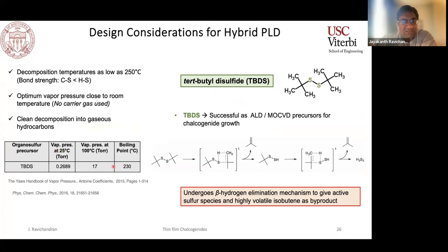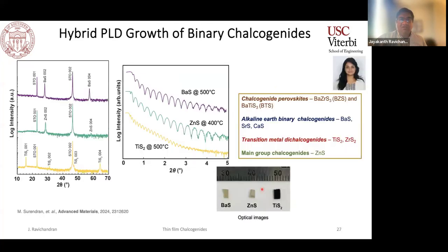And we went through this whole list of precursors, and we identified tert-butyl disulfide as a good choice because you do get fairly appreciable vapor pressure at modest temperatures like 100 degrees Celsius. And presumably, if you have a single sulfur connecting alkyl chains, the cleanliness with which they cleave and interact with your material seems to be significantly better with tert-butyl disulfide. And that's why it's also widely used as an ALD or MOCVD precursor for chalcogenides. So we learned about this beta hydrogen elimination mechanism, which makes this much more conducive to getting cleaner, nicer growth of these materials. So we chose this as our precursor material and we started trying to do some growth.